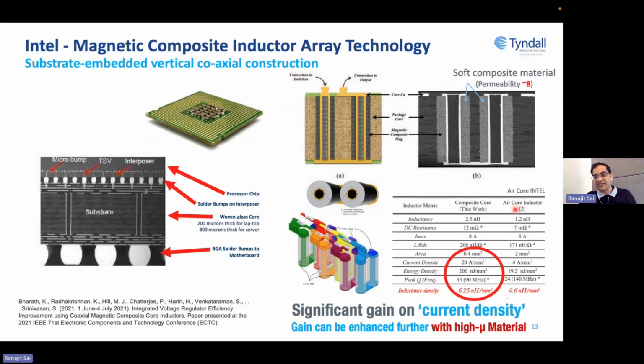Something like the current density has gone up by 5 times, and inductance density has gone up almost 10 times. That was amazing. However, here the permeability of the material is just 8. It is being operated around, say, 80 megahertz, 90 megahertz, in this kind of high frequency range, but the 8 is good enough at that frequency. So that's how it has evolved along the two of the big industries, and there are so many other industries that have looked into this particular technology.